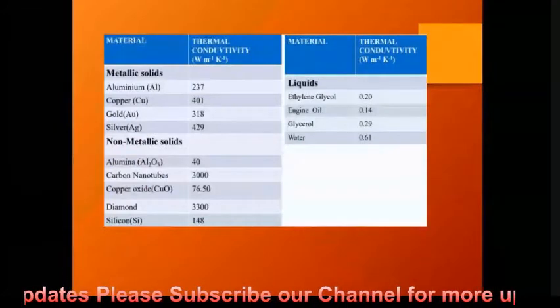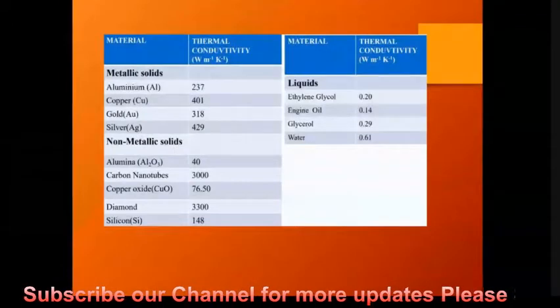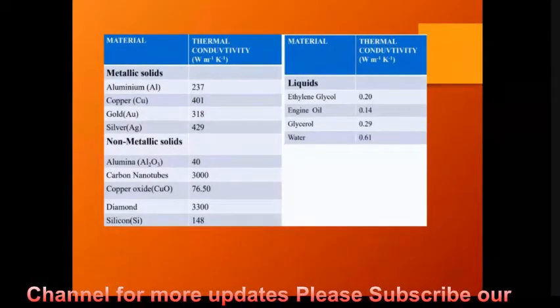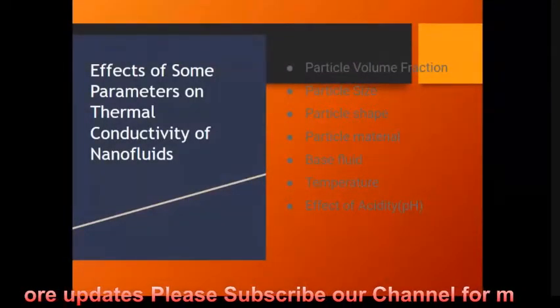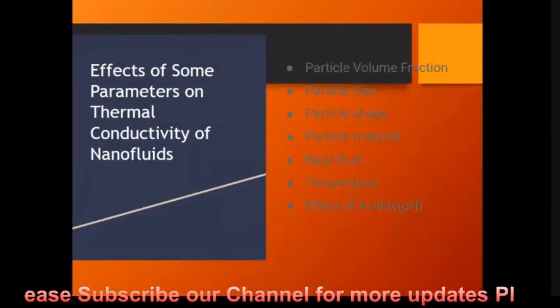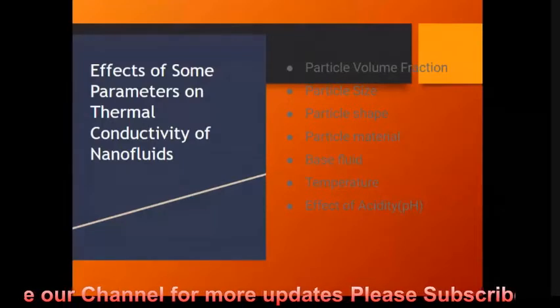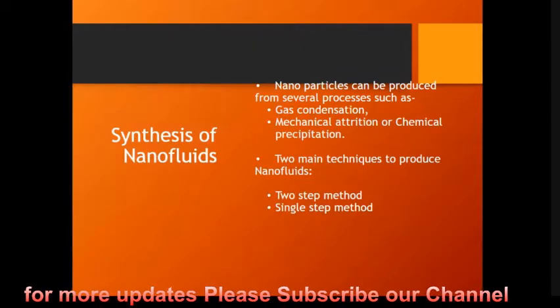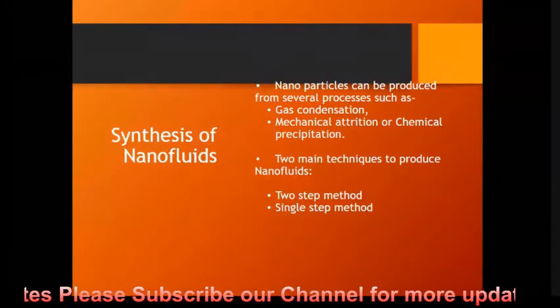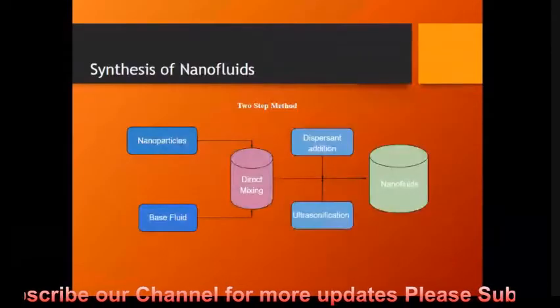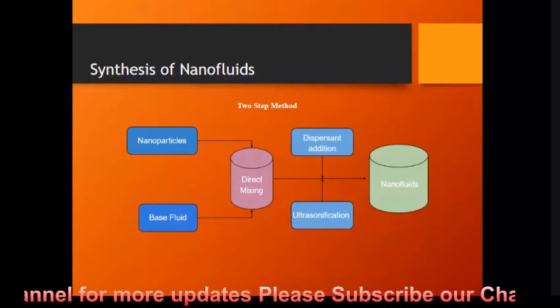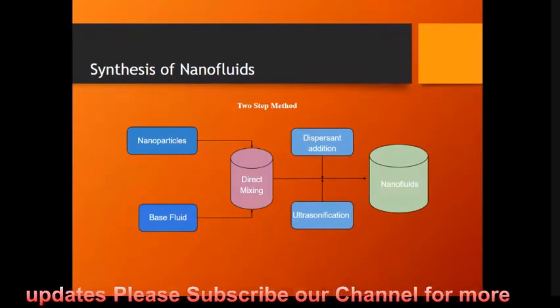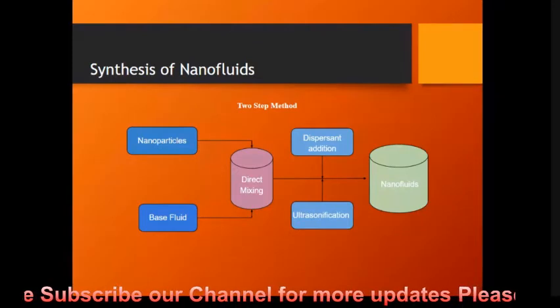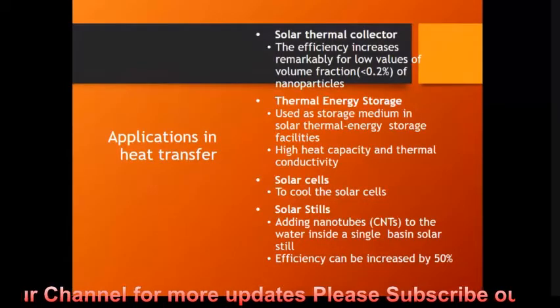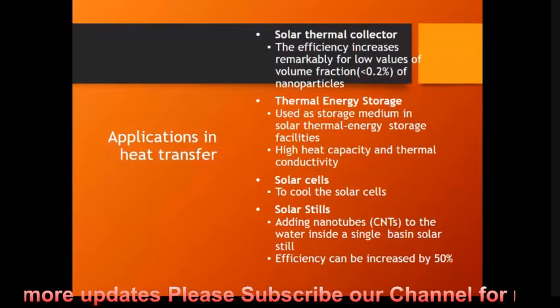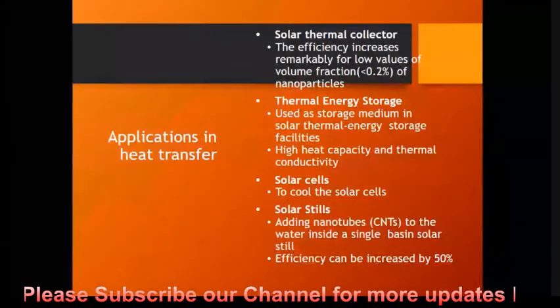So of course, we can have a look at the thermal conductivity of basic materials: metallic solids, non-metallic solids, and liquids. And if you look at the effects of some parameters on thermal conductivity of nanofluids, it talks about particle volume fraction, particle size, particle shape, particle material, base fluid, temperature, and the effect of acidity, that is, pH also. Then synthesis of nanofluids, of course, one of the very important steps, by using the two-step and single-step methods. In the two-step method, we have the nanoparticles in the base fluid, direct mixing, and ultrasonication and dispersant addition so that you can get a nanofluid. Single step method. Then applications in heat transfer: solar thermal collectors, then thermal energy storage, then solar cells and solar stills also by adding carbon nanotubes.